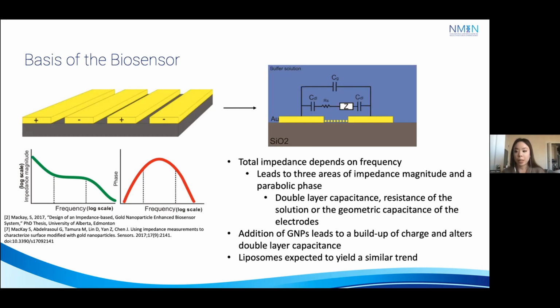And gold nanoparticles have been shown to provide a capacitive change when bound to the surface between the electrodes on that silicon dioxide surface due to the buildup of 2 layers of charge caused by the gold nanoparticle and surrounding solution. And this should result in an increase in impedance and a downward shift in phase, which can be observed in our graphs. And liposomes are expected to yield a similar effect, although not as robustly documented in the research.